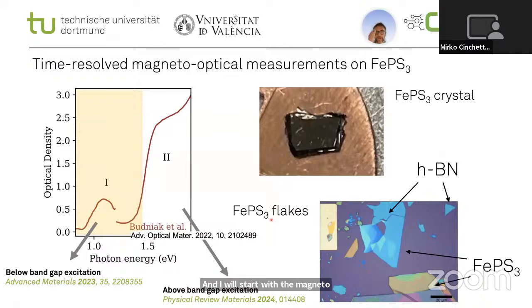We performed a bunch of experiments using excitation below and above the band gap, that are reported in these two papers. Today, I will discuss only the experiments with below band gap excitation. And we use either crystals or also exfoliated flakes on hBN that were produced at the University of Valencia by the group of Eugenio Coronado. Of course, if we use the flakes, we also have to characterize them, for example, determine the thickness, but also check using Raman spectroscopy that they are intact, so that they have the same Raman spectra as the bulk crystals, and this we did.